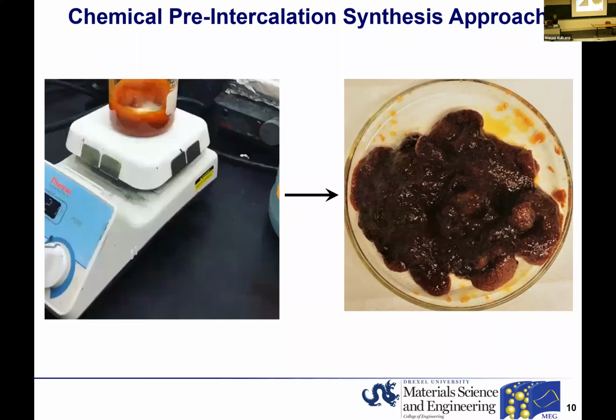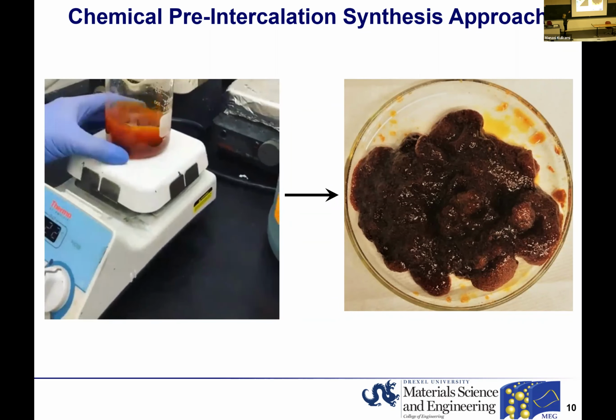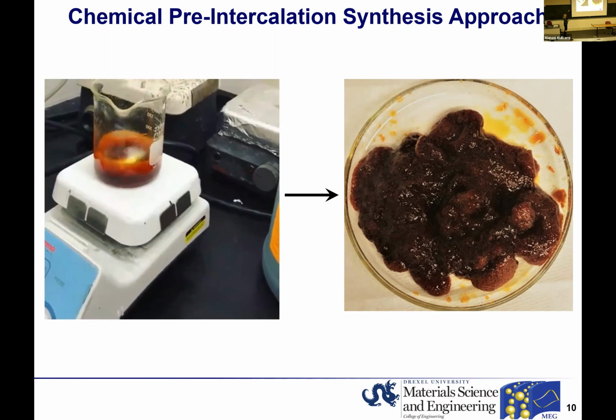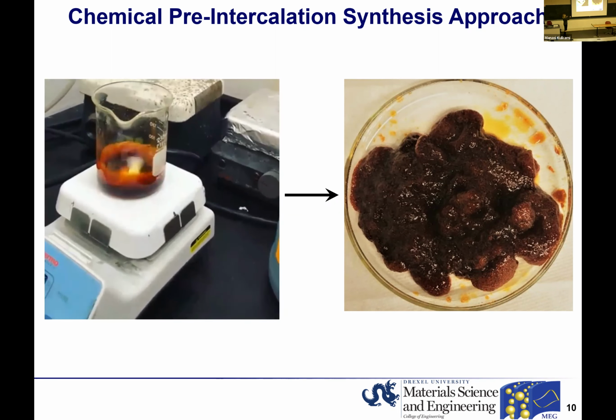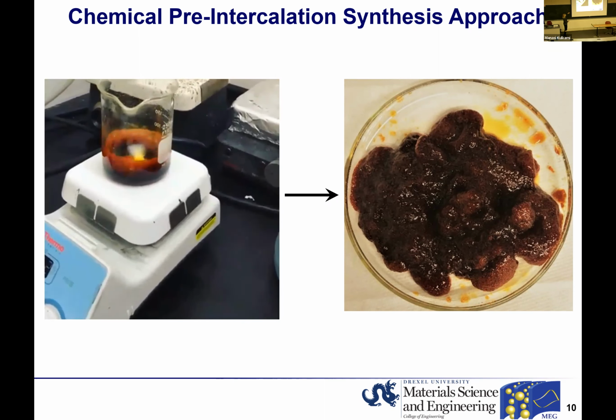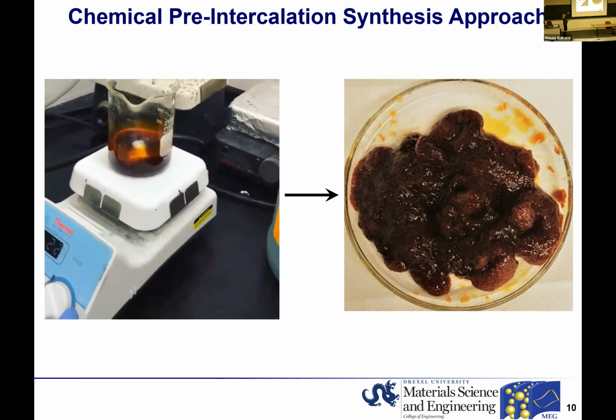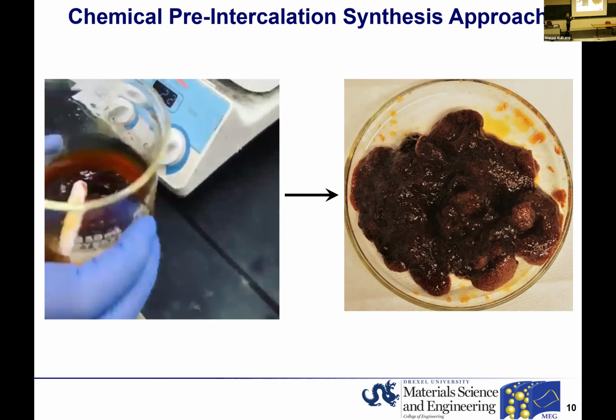But before I show you the result, I just wanted to mention that this is a very simple synthesis. It's just a beaker on a hot plate, and you see a student adding some precursor into the mixture of water and hydrogen peroxide. You see some bubbles. This is due to the peroxide decomposition. And essentially the color changes indicate the sequence of these hydrolysis and condensation reactions that occur in the system. The product is just a substance looking like this, which sometimes my students call raspberry jam. So my research has a lot of analogies with cooking, because we also add salt into our synthesis. For example, sodium chloride, at some point we just used the one bought in the supermarket, and it worked.